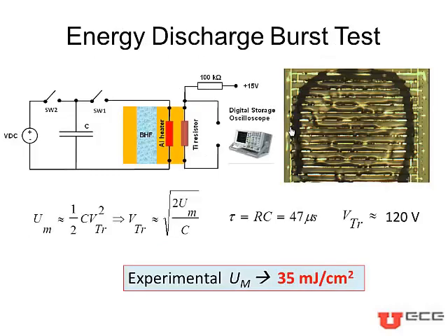We can also experimentally measure the melting energy using the energy discharge burst test. In this experiment, we charge a 0.47 nanofarad capacitor with a voltage V and then discharge the capacitor onto the heater. The minimum melting energy is equal to that energy which produces substantial visual damage onto the sample. When we conducted this experiment on a glass wafer chip, the minimum energy turned out to be 35 millijoule per centimeter square, which is in rough agreement with our calculated value.